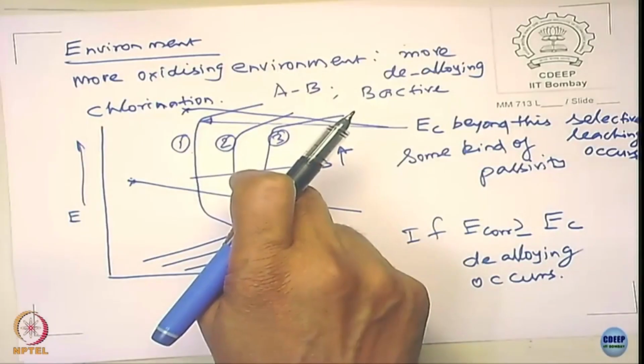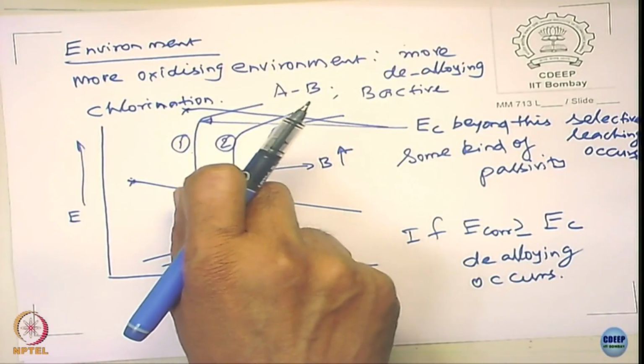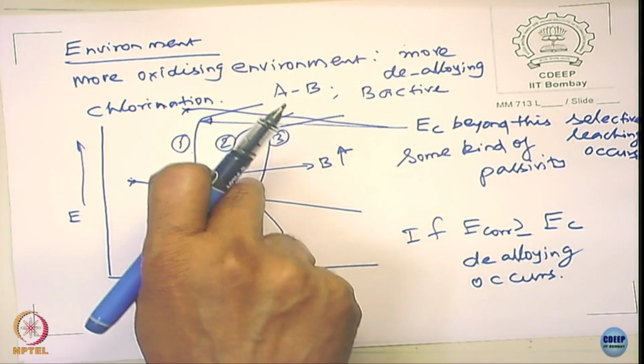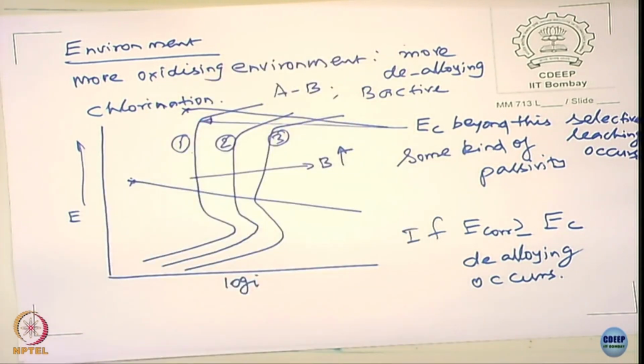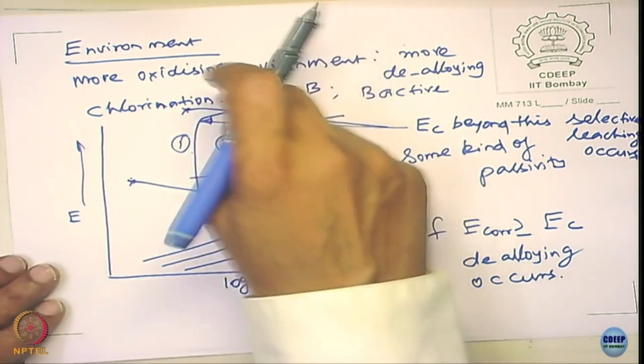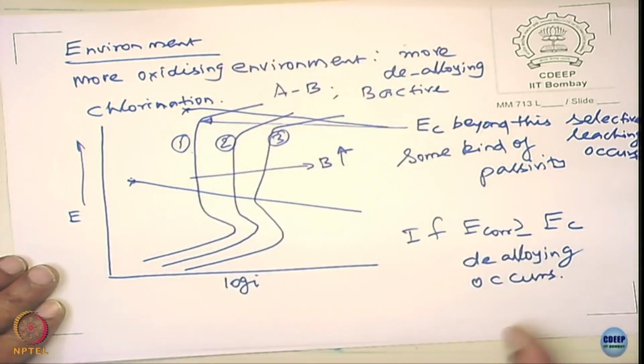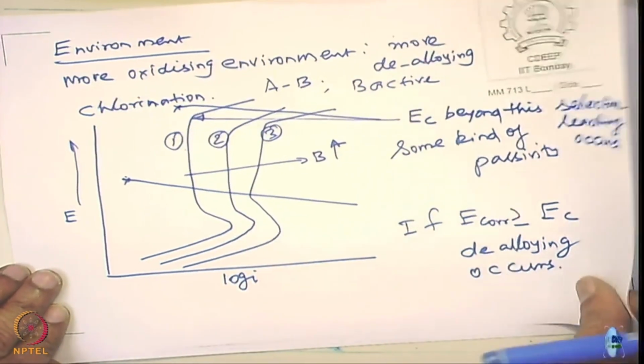In fact, if you take a copper-nickel system, carry out a polarization and see the solution, the color will turn green. Why? Because more nickel is getting dissolved. So you see a nice green coloration at this particular potential. You may see nickel also here, but the amount of coloration is very small. That's where you can show that nickel is preferentially dissolving over this range of potentials. Hope this point is clear to you.